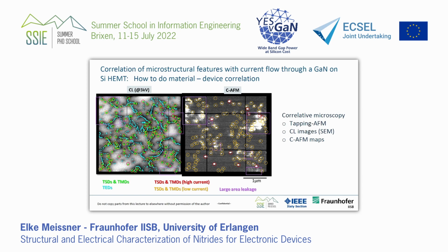And we can also distinguish between the types of dislocations: threading dislocations, edge dislocations, mixed types. Then we say, okay, we have high current, low current flow. And we put everything together and on top of each other. We say, okay, those are areas with large leakage where we find nothing in structure. We don't really know what this is. So this is unclear. This may be a technological issue, not coming from the material. But otherwise, we can make a one-to-one correlation. But imagine that this is on a micrometer or nanometer scale. So whatever you characterize at SEM in a larger sample, you have to find back the place in AFM on a micrometer scale. And you don't have a microscope like it is at the SEM.